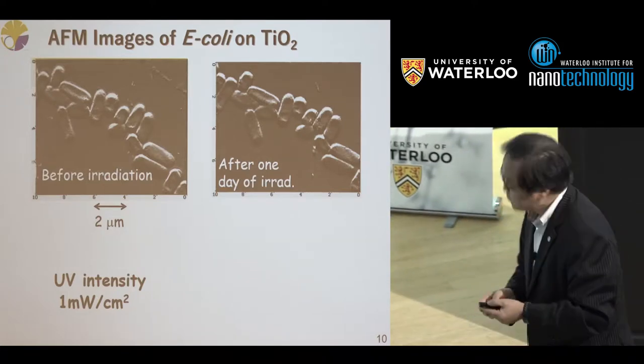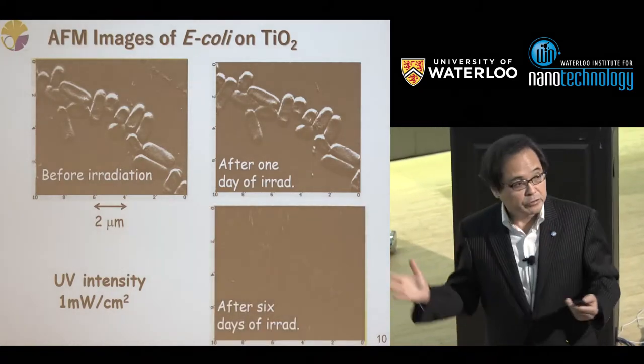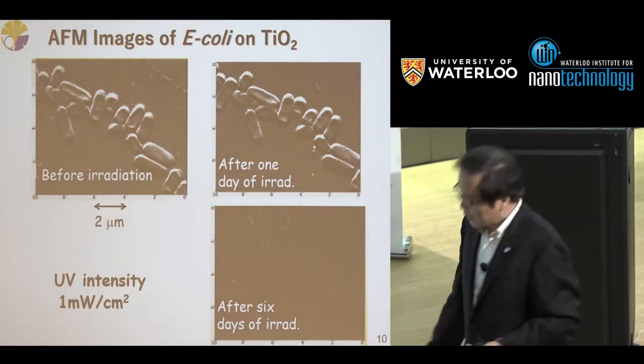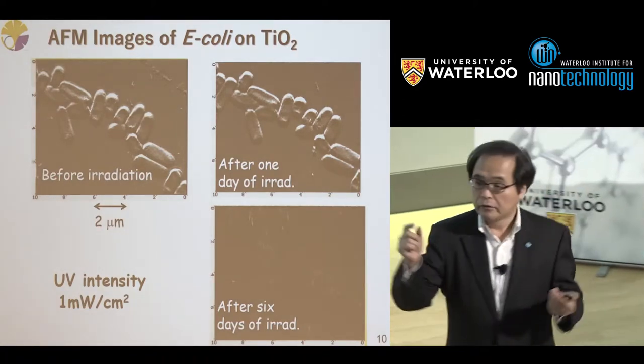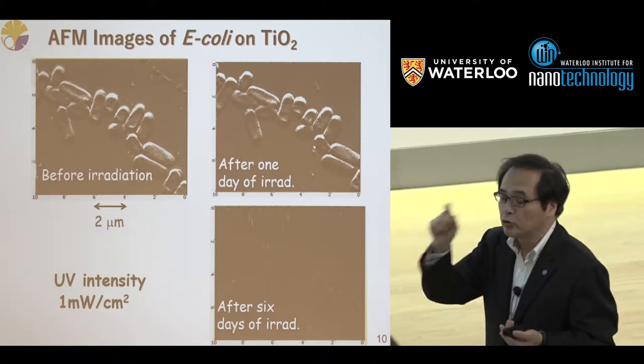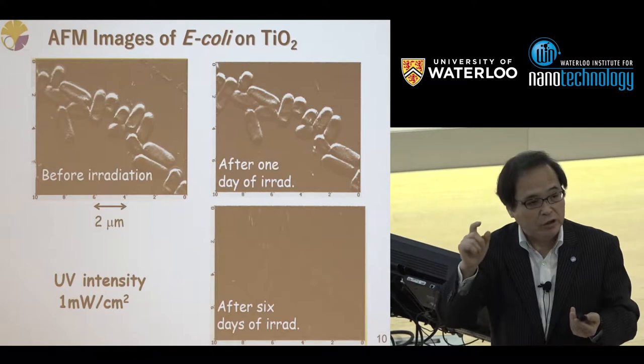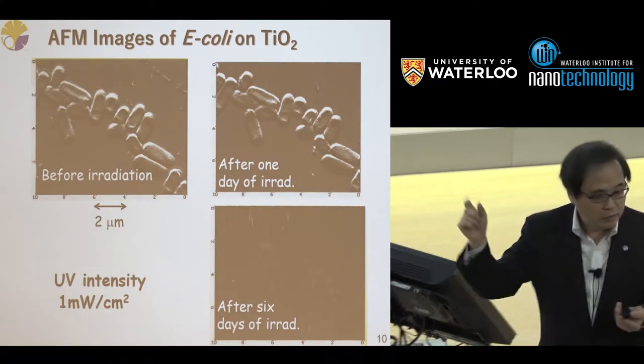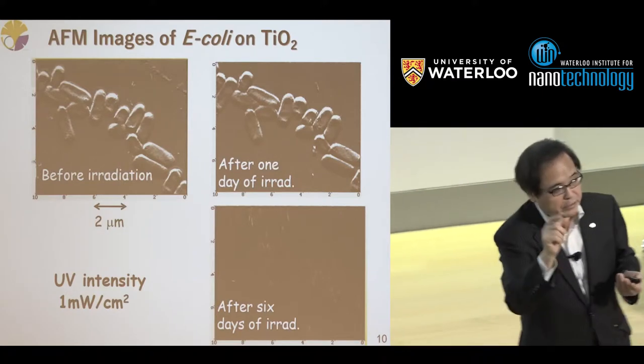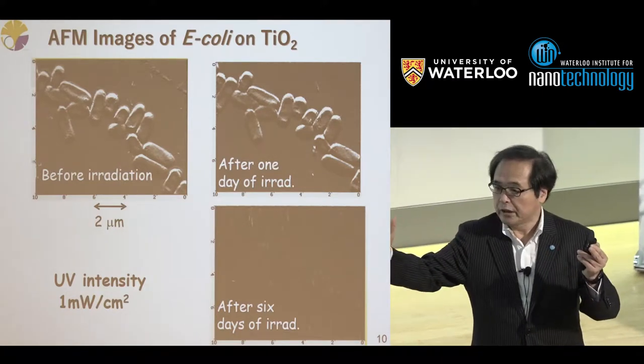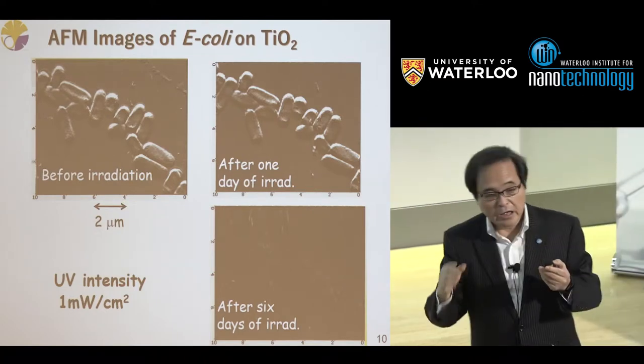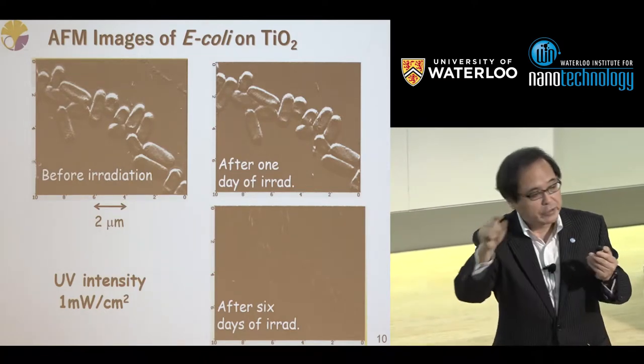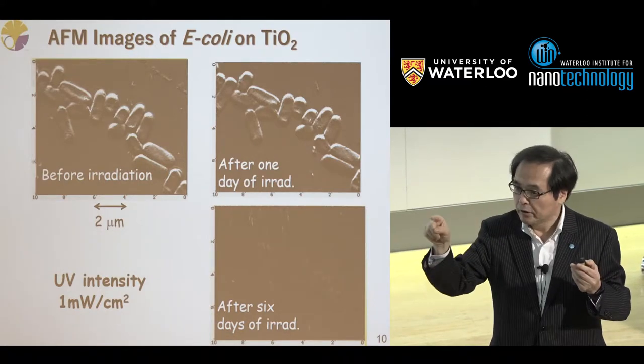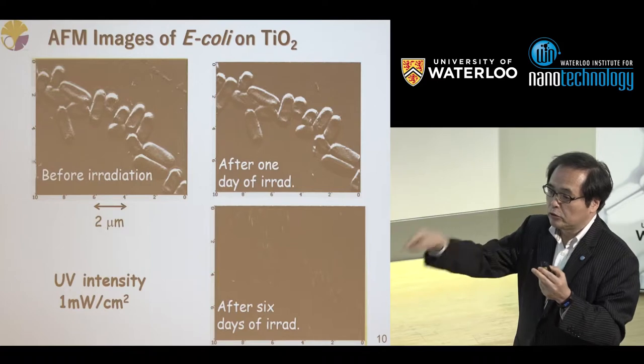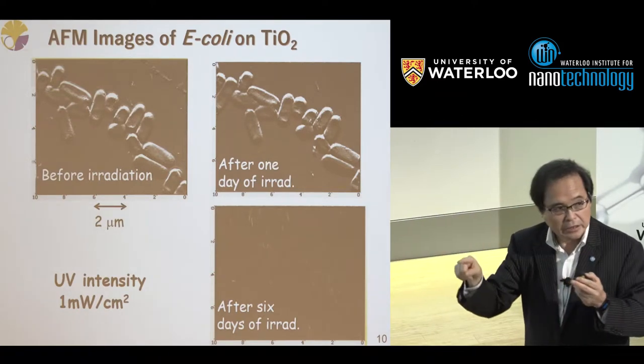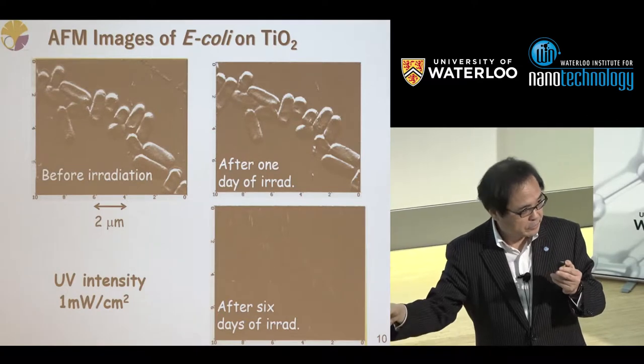Keeping the illumination, after 6 days, the bacteria disappeared. Okay, let us calculate again. When we decompose a cockroach, it took 2 years with a light intensity of 20 milliwatts, 20 times higher. The time period of irradiation here is 6 days, and for the decomposition of the cockroach, it took 2 years, 700 days, so 100 times. The total amount of photons introduced here is 2,000 times less than in the case of the cockroach.